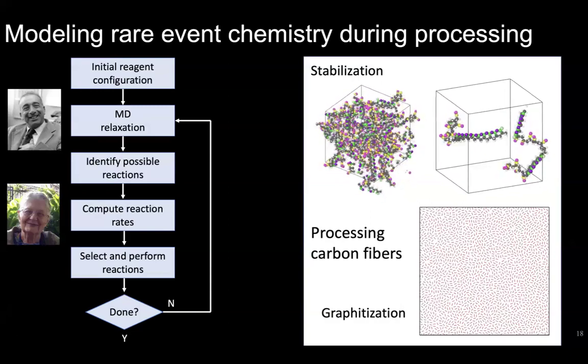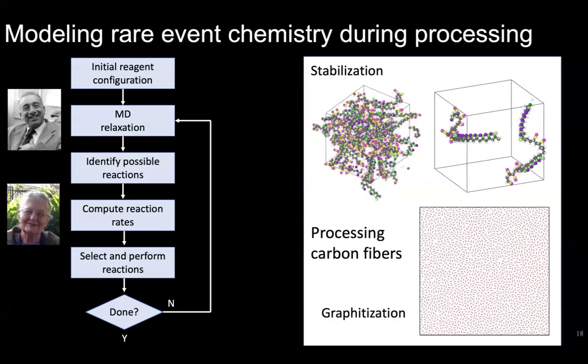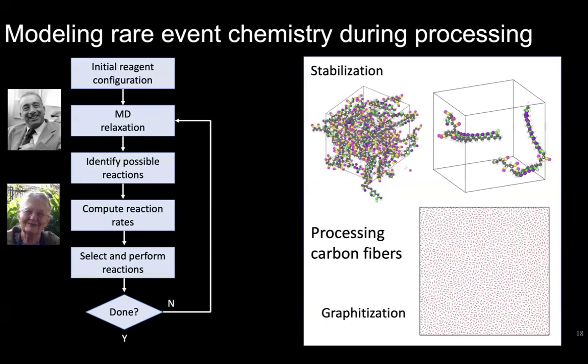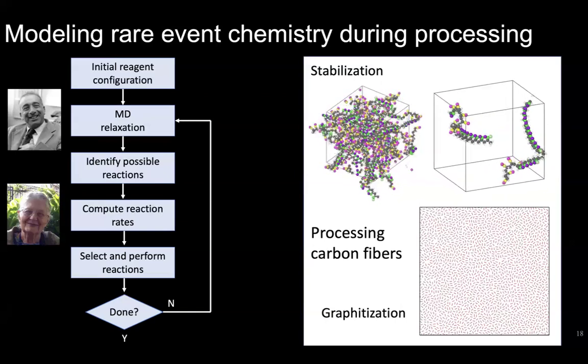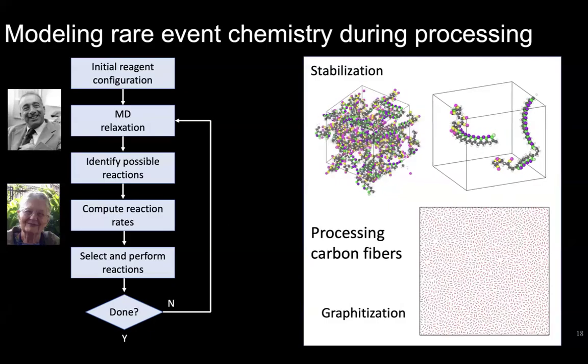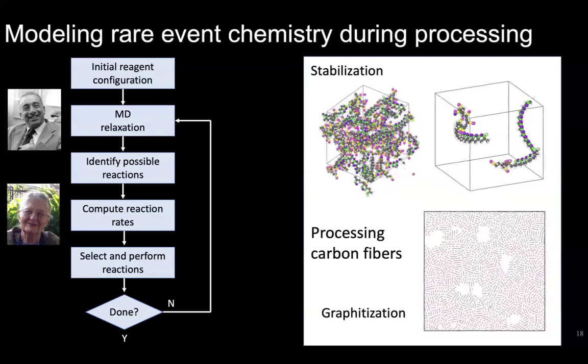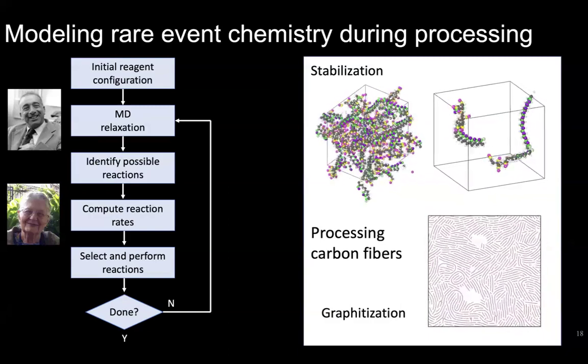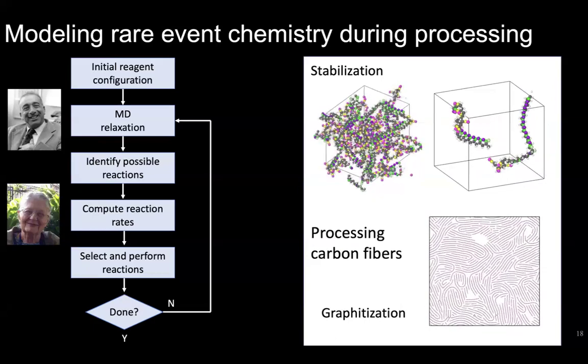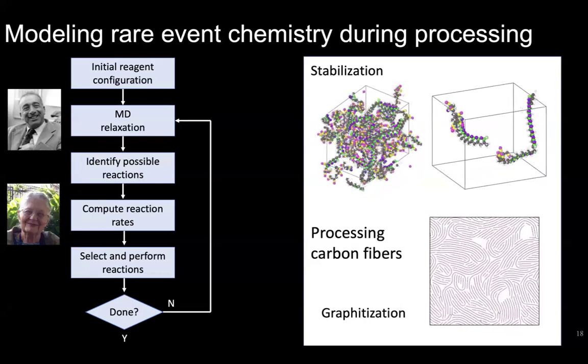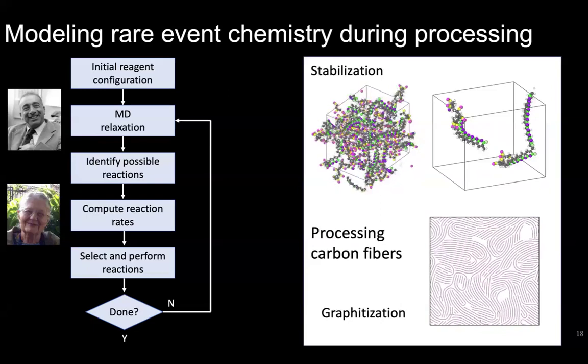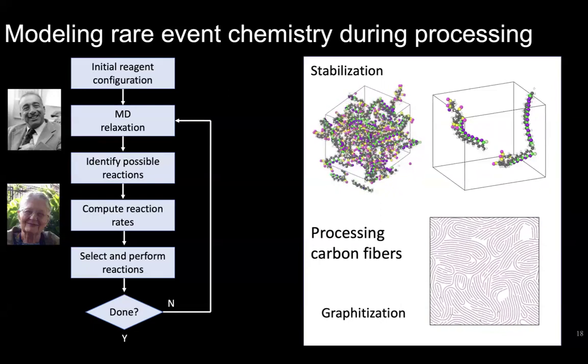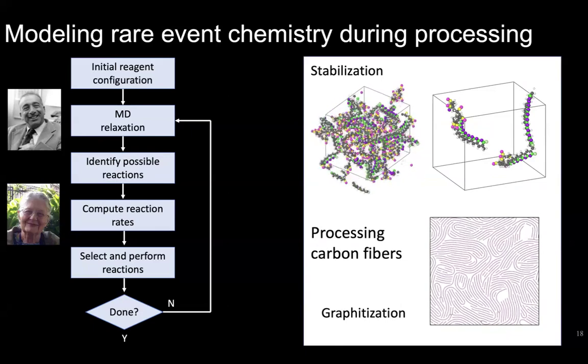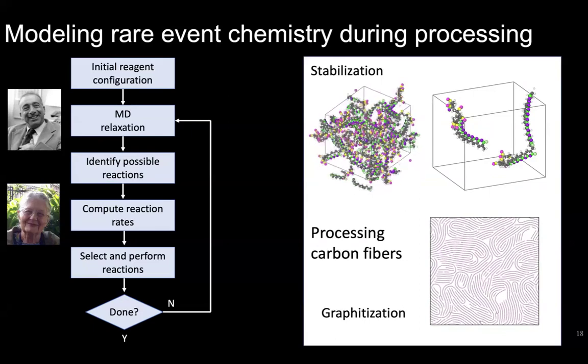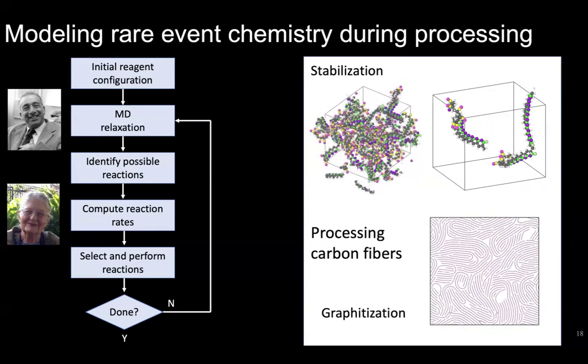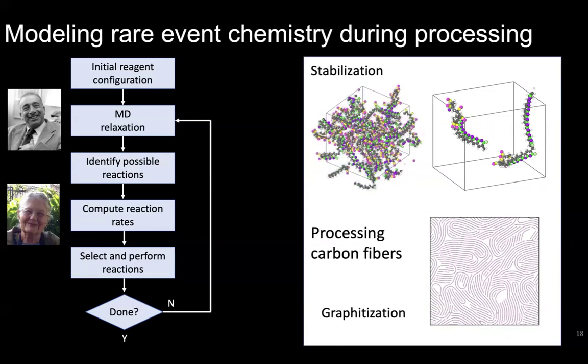So now I have this stabilized structure, and now I can do the process of carbonization. This is in a different paper. What you see here sticking out are the ladder structures coming towards us. So this is a cross-section of what's going to be the carbon fiber. And we do the same thing, and we start going through graphitization, carbonization, and we create the cross-sectional picture of the carbon fiber, okay? If you remember the picture I showed you before of the cross-sectional area, we see the same features, we see the same defects, and our simulations predict the right transverse modulus.